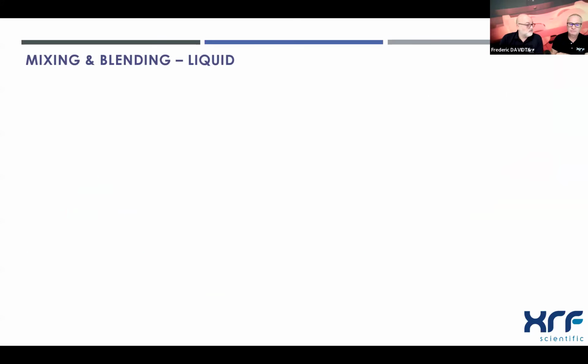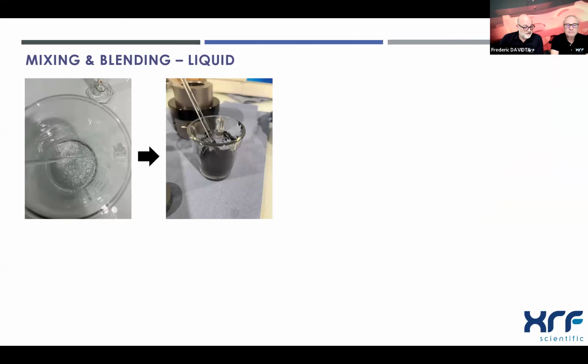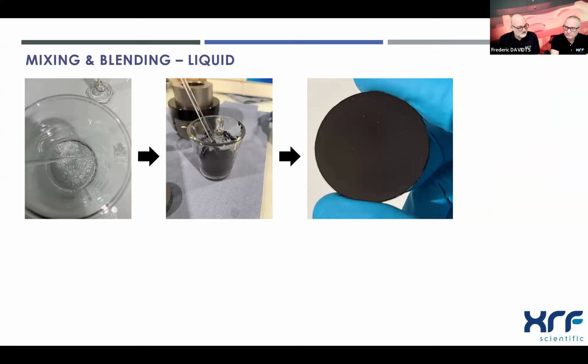So now the case of liquid. So we have some fusible plastifier that can be mixed with a solvent to produce a solution. You will add it to the sample powder to be able to produce solid tablets after drying. So the big advantage, it takes a little bit of time, but the big advantage is really that you make a solid plastified pressed powder. So it's very strong, and it's used for the fluffy powder, very pulverized powder, like black carbon, coal, that are